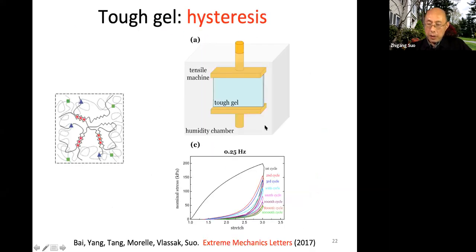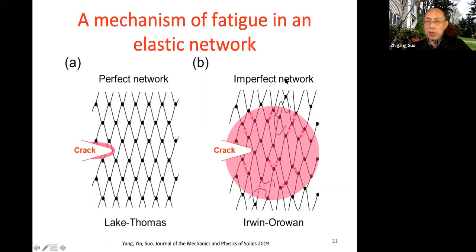However, if you have a realistic network, a realistic network is not perfect. So some chains are shorter than other chains. So this black chain may be longer. This chain may be shorter. So when this crack is coming here, maybe this chain doesn't break. You already broke this chain because this chain is too short. So when you do monotonic loading, all these short chains really contribute to toughness. That's why you have toughness, high in this case, 100 joule per meter squared.